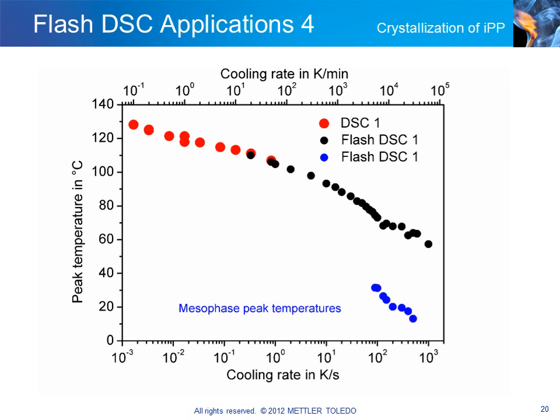The results from the two techniques show very good agreement in the range of overlap between 0.2 and 0.8 degrees per second. The measurement curves recorded at cooling rates above 50 degrees per second show the presence of a second crystallization peak at about 30 degrees Celsius. Other metastable structures are apparently formed at these low temperatures. The corresponding peak maximum temperatures are shown in blue.